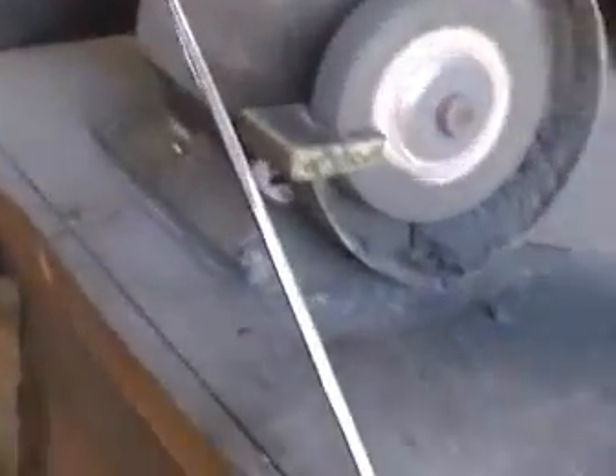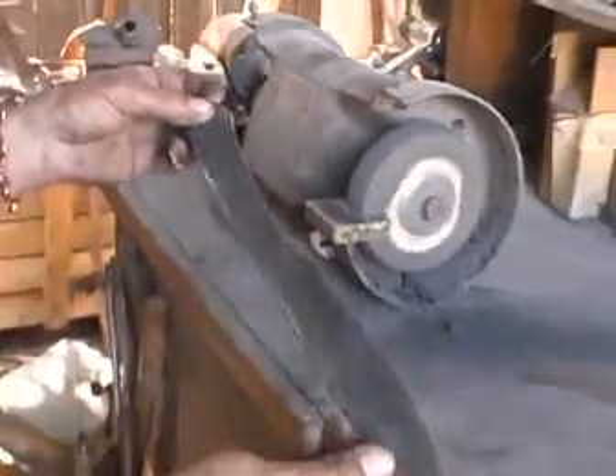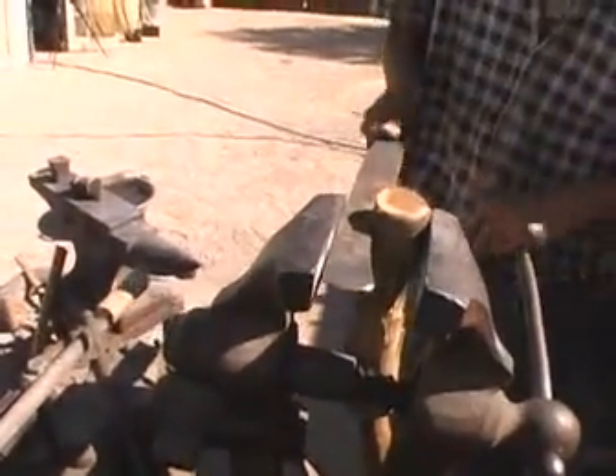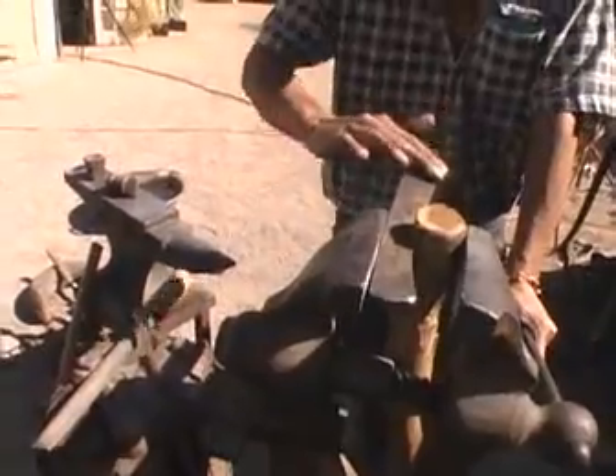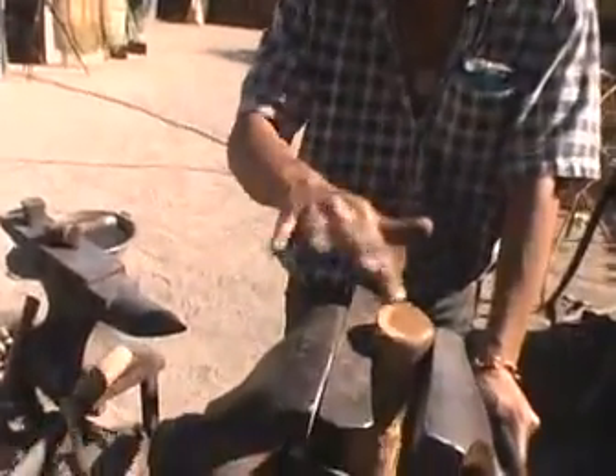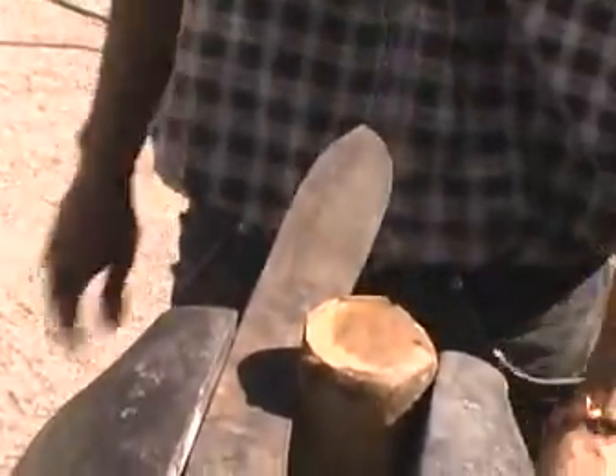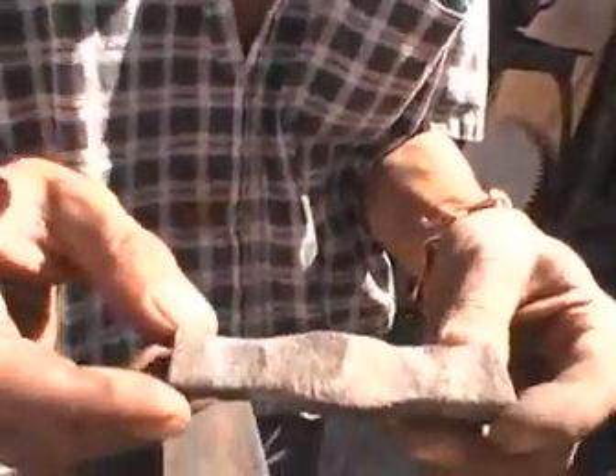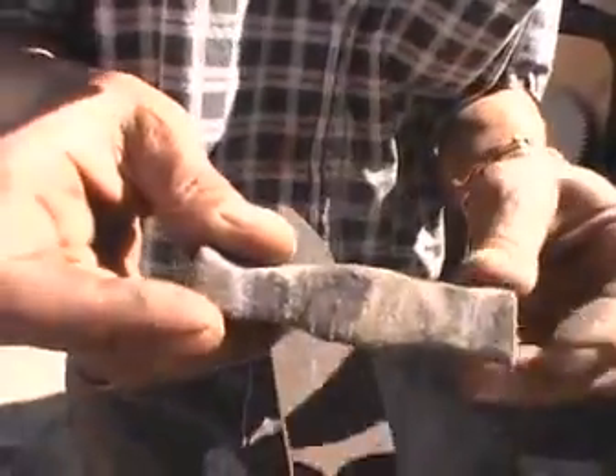Now I'm going to file it a little bit over in the vise. This is just to get rid of the grinder marks and straighten out all the angles and the contour of the blade a little bit. I'm just using this so I can clamp the blade tight. Before I scrape it, I usually use just a coarse stone and just take some of the scale oxidation off the surface, because that'll wear the scraper and the file out real quick. This is just a coarse stone, and I'm going to use this to get some of the scale off before I scrape the edge.